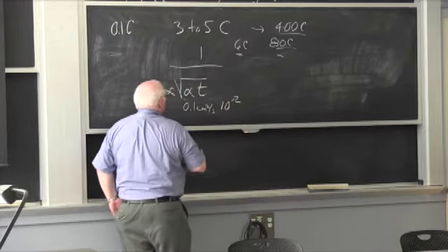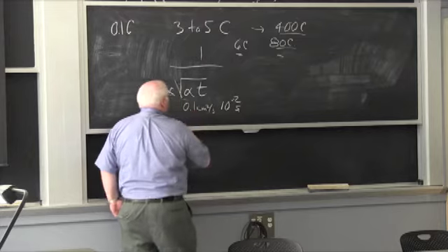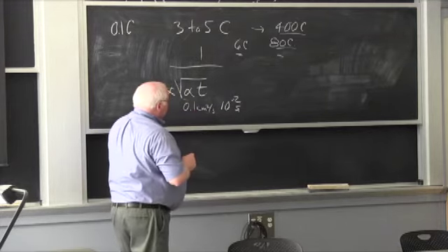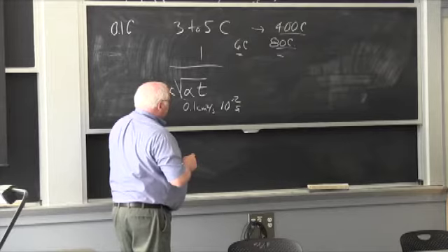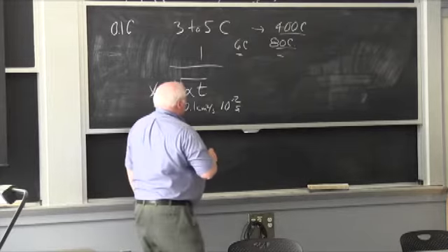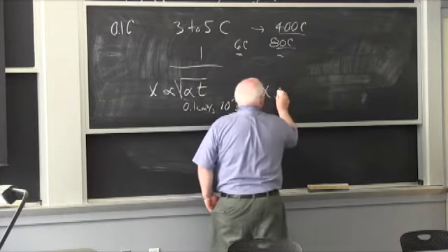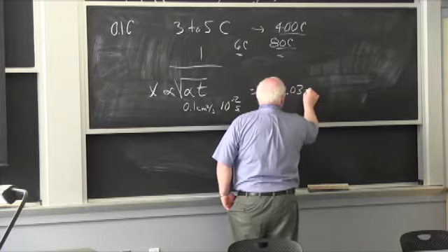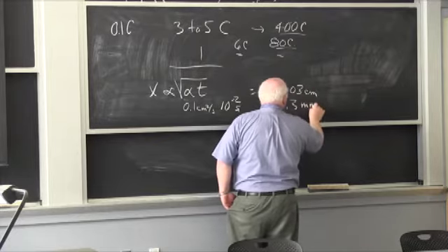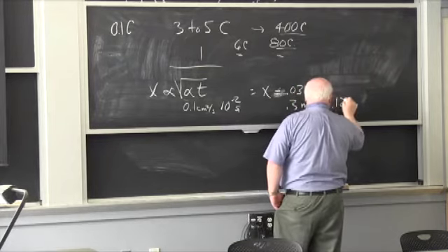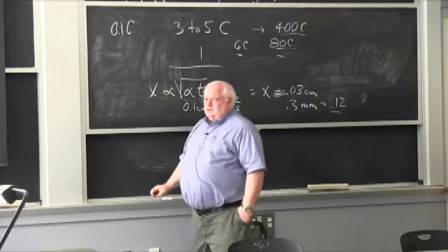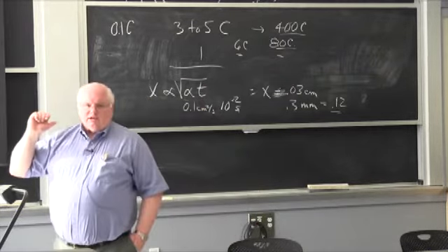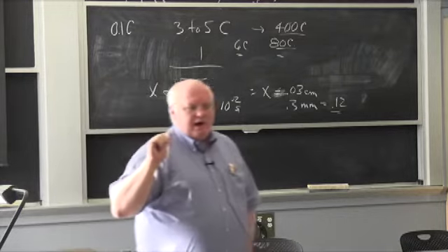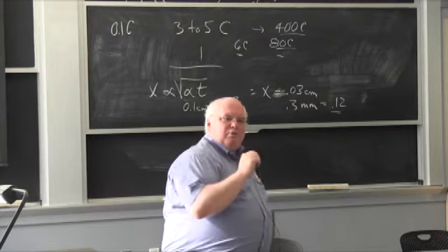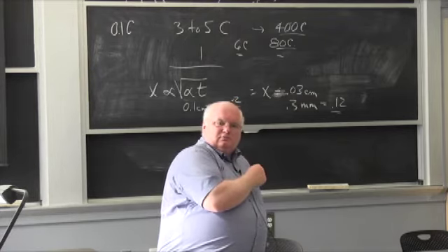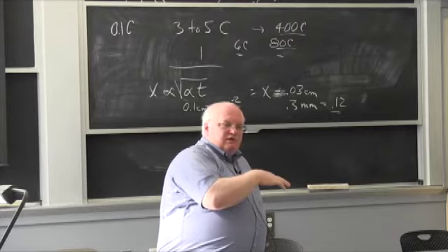So I have the square root of 10 to the minus 3, which is what? 10 to the minus 3 is 0.03. X is equal to 0.03 centimeters, which is 0.3 millimeters, which is 12 thousandths of an inch or so. The CSST is 10 thousandths of an inch, so it will blow through CSST in the typical time that you might have, but it won't blow through black iron pipe, which is 1/8 of an inch, which is 10 times thicker. Okay? Now, in fact, I kind of simplified some of the heat flow here.